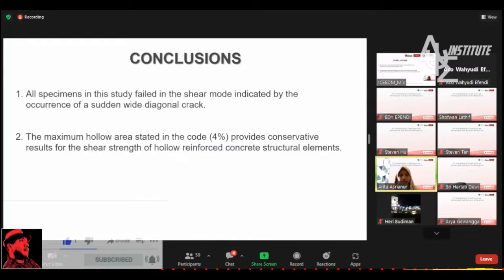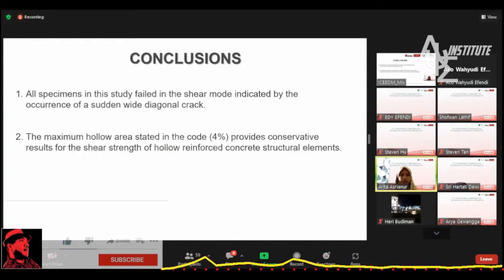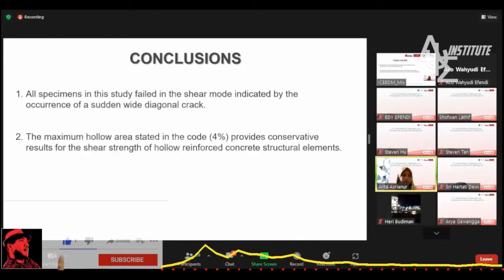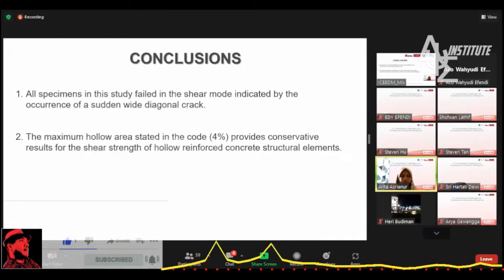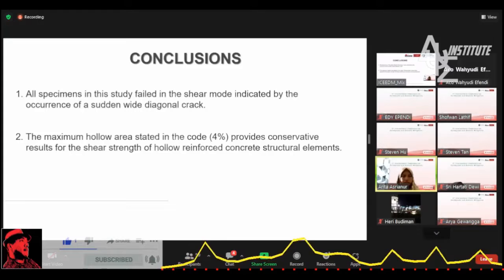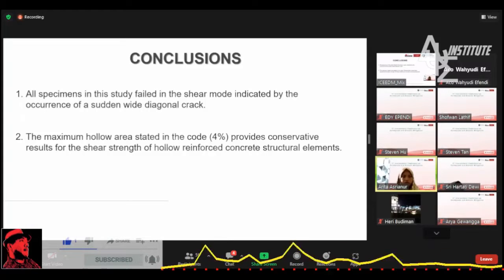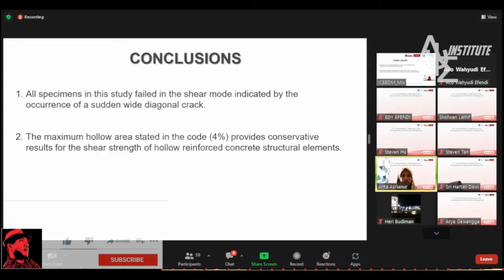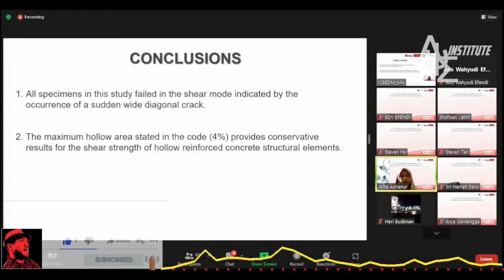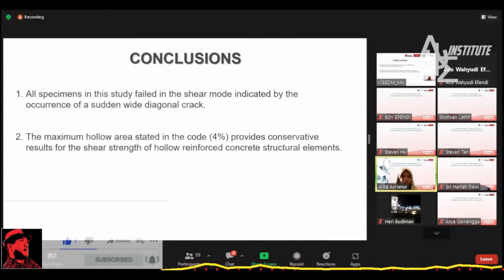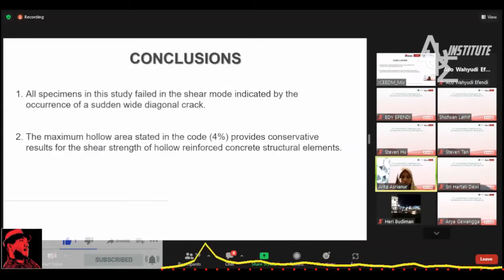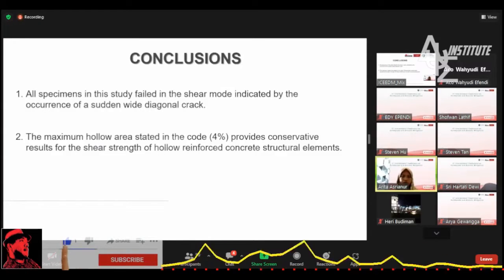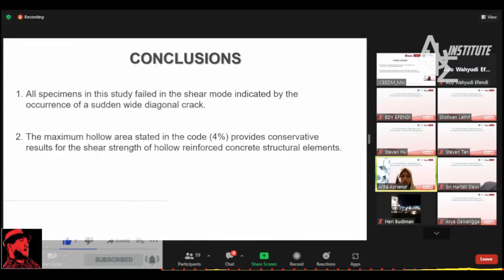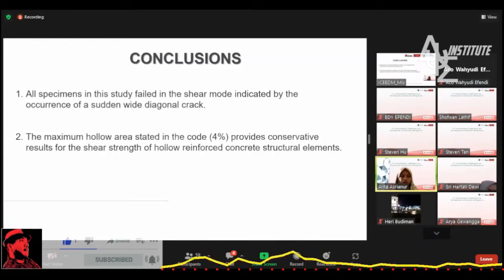For the last, it can be concluded that all of the specimens in this study failed in shear mode, indicated by the occurrence of a sudden wide diagonal crack, and the maximum hollow area stated in the code, 4%, provides conservative results for the shear strength of hollow reinforced concrete structural elements.